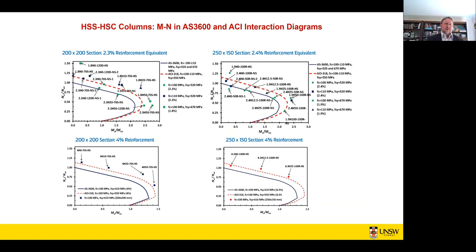All right, so let's have a look at the results now. And I've plotted here two curves. The solid line here, perhaps look at this bottom left one, a bit more clear. The solid bottom line here, that's the model with AS3600. And the dotted line there is ACI 318. Now, it appears that ACI 318 is a better predictor. Problem is ACI 318 is a poor foundational model for high strength concrete. It was developed for members of 40 megapascal concrete. It was never changed. And you see in many circumstances, so these little green dots here, the green dots are for a 520 megapascal longitudinal steel, so conventional strength longitudinal steel.